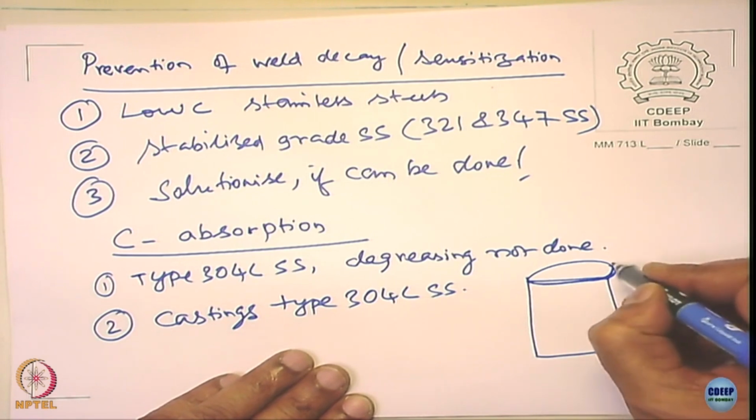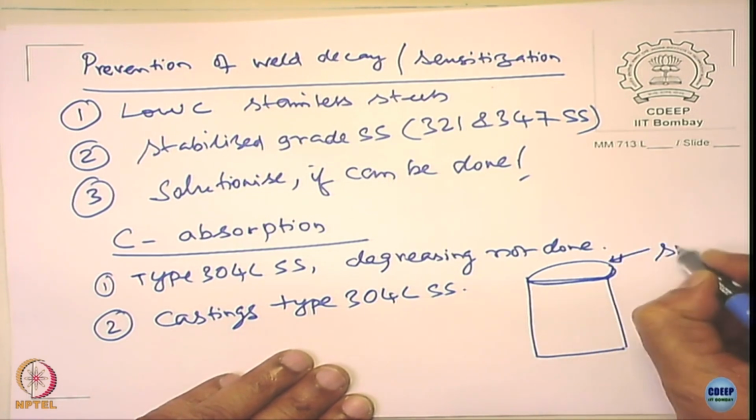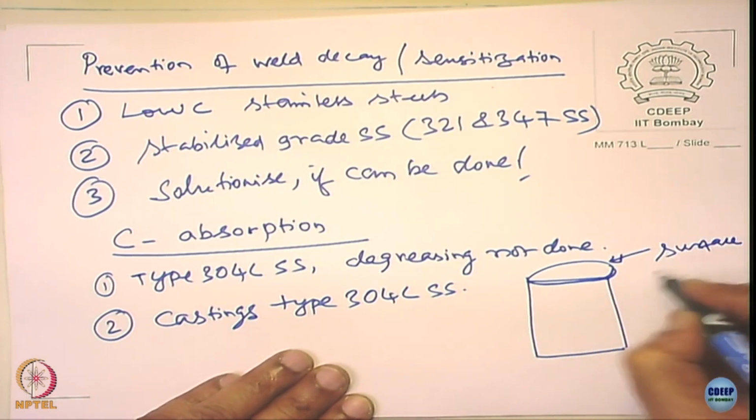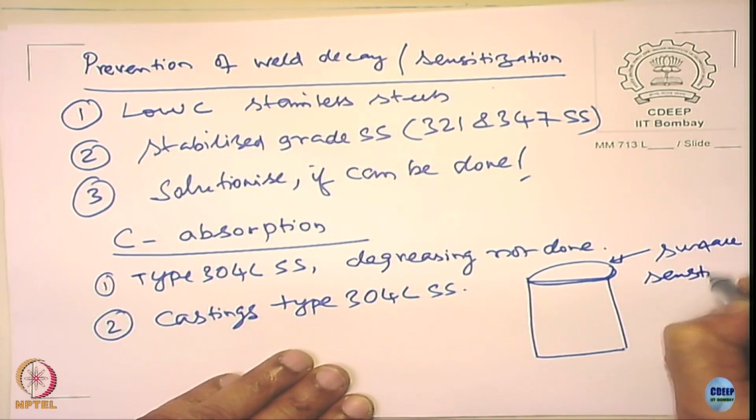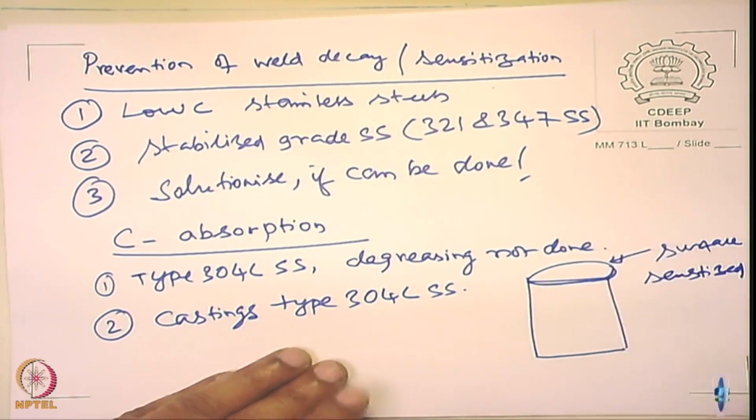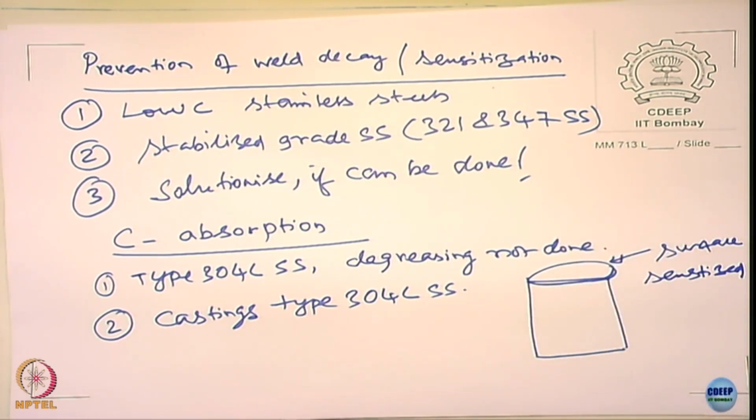So, very interestingly, the surface is sensitized, the center looks fine, and as you start moving inside, the extent of sensitization decreases. Please note, it is casting.